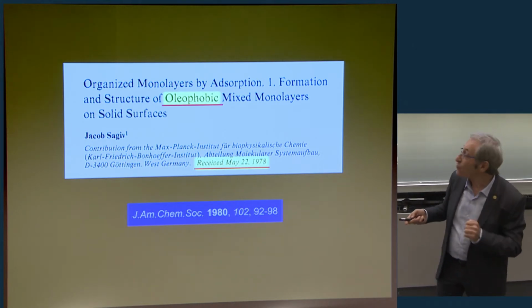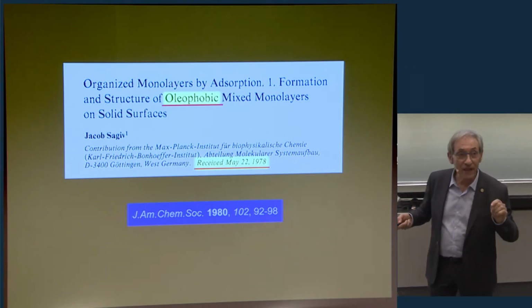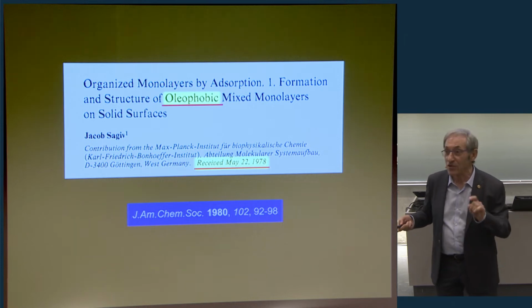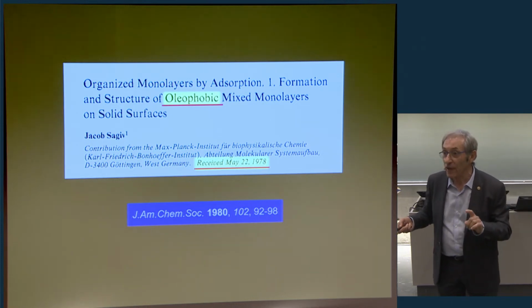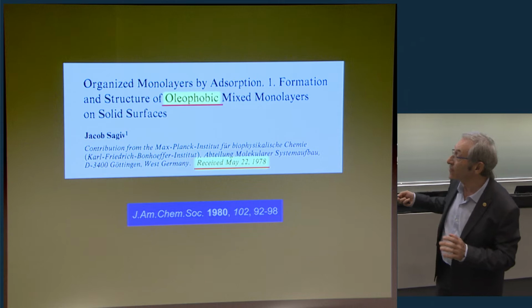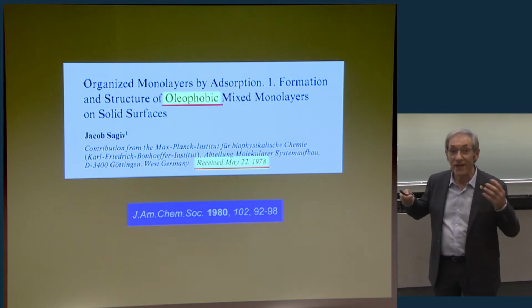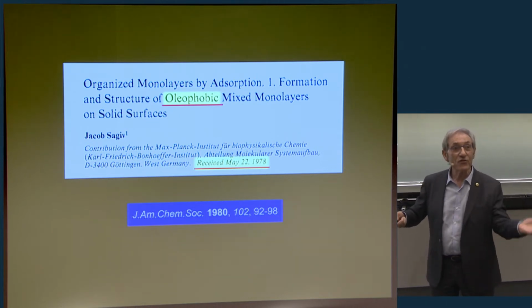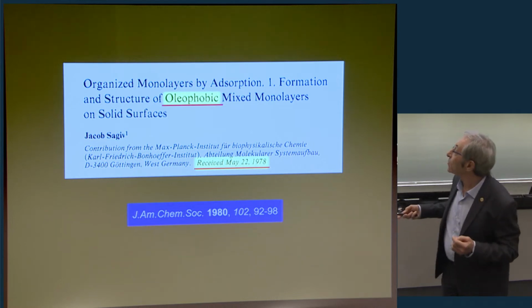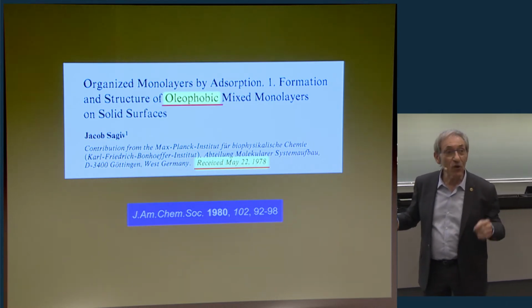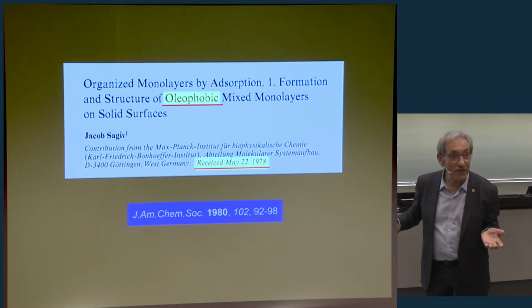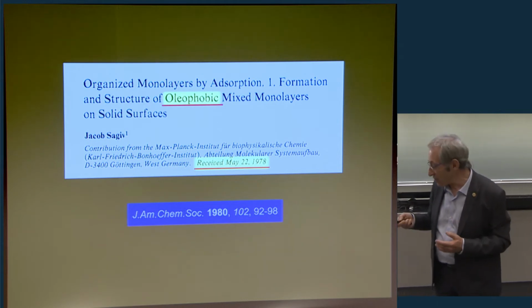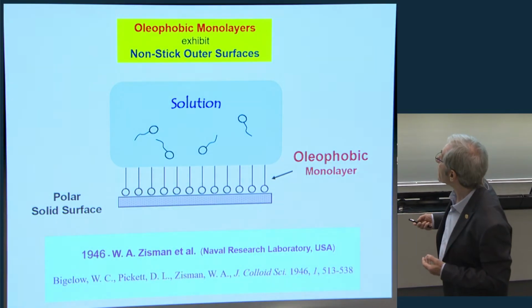And this ensures that no more material adsorbs on the surface after the formation of a well-defined monolayer. So this is a key feature for self-assembly of a well-defined monolayer, because if the surface is not a non-stick surface, more material would stick to the surface, and you cannot get a well-defined monolayer.